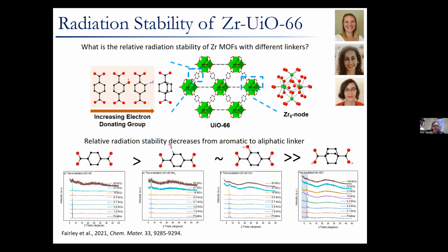So we see that the original zirconium UiO-66 with the BDC linker, all the way over on the left-hand side, was the most resistant or the most stable in these radiation fields and lasted up until that 95 megagray. And then as we go across to the right-hand side of the screen, you can see the linker with the aliphatic nature barely makes it past 6.2 megagray before we see a significant component of that amorphous material.